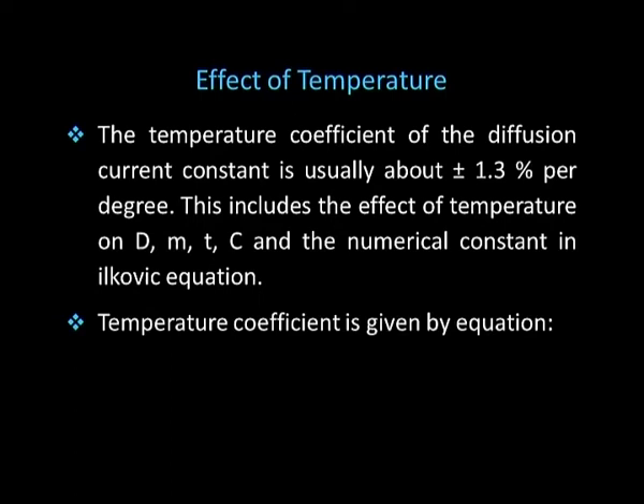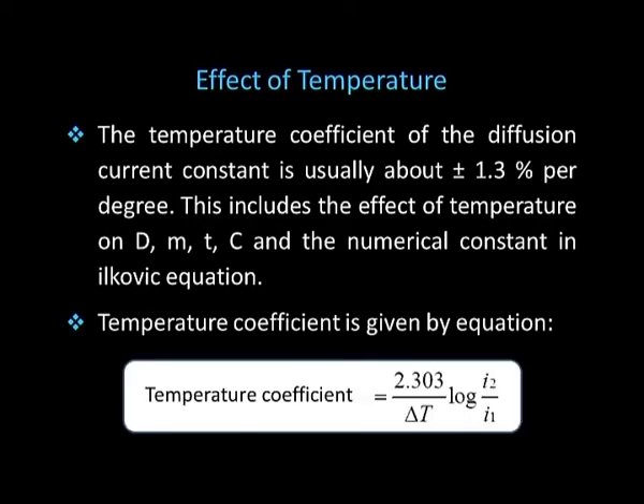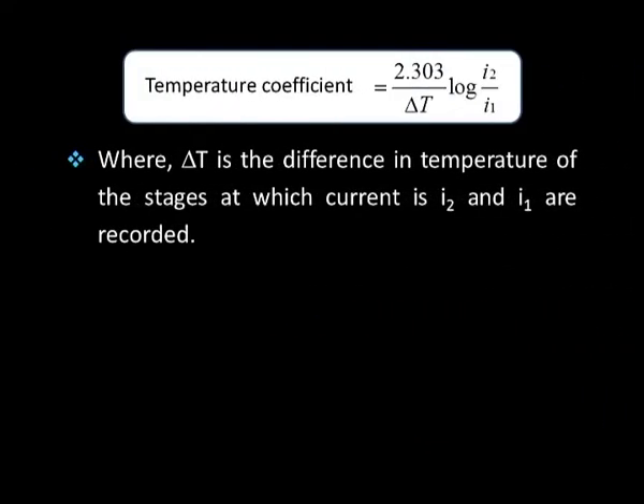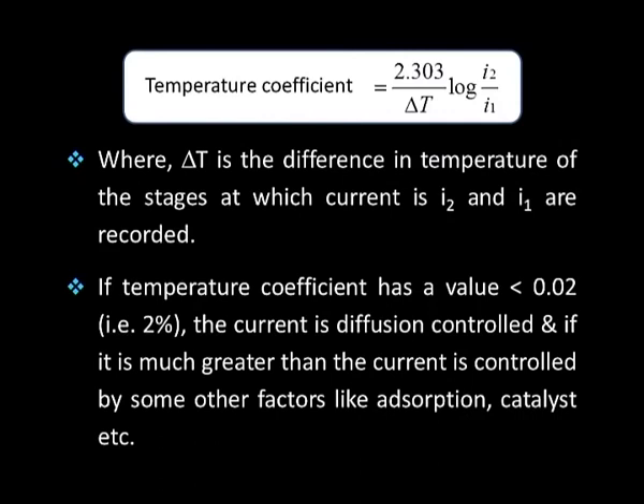Temperature coefficient is given by an equation. Temperature coefficient is equal to 2.303 divided by delta T log I2 by I1, where I1 and I2 are the currents at temperature T1 and T2. Delta T is the difference of temperature at which current is I2 and I1. If temperature coefficient has a value less than 0.02, that is 2%, the current is diffusion controlled, and if it is much greater, then the current is controlled by some other factors like adsorption, catalyst and so on.